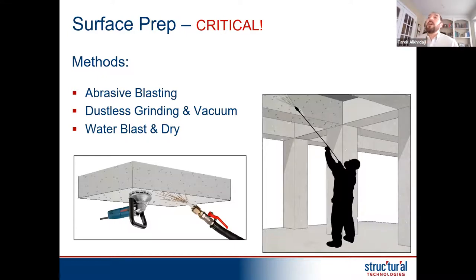In terms of application, if you think about all these applications I just described to you, it all depends on this high strength material bonded well to the concrete substrate. Therefore, it's very important to bond the material to a good concrete, not concrete that's been exposed to the weather and contaminated, and has been painted or has on it material that comes maybe from the foam release agent that they use sometimes when they do foam work, etc. And sometimes, when you place concrete, there's bleed water and loose material that come to the surface. So you try to get rid of all this outer layer of concrete before you install the FRP. That can be done by abrasive blasting, such as sandblasting or hydroblasting.